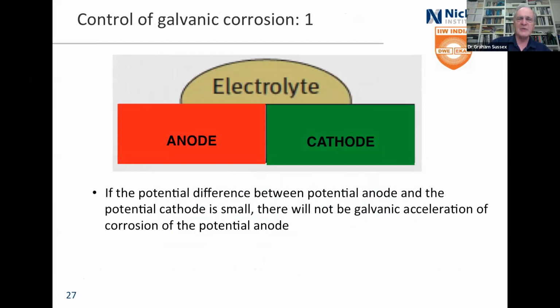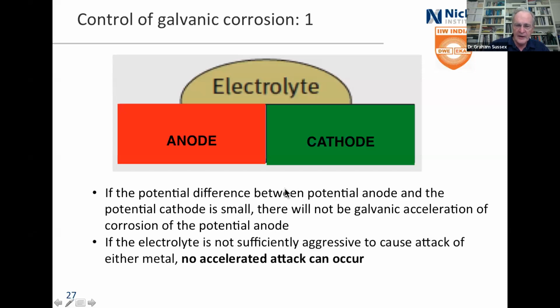So this comes out of a Euro Inox publication, and there's the reference table at the end. It's basically giving the definition of galvanic corrosion. You've got an anode, you've got a cathode, and you've got an electrolyte sitting on top. It doesn't talk about the 4 steps, but the bit down the bottom that's critical is that one of these has actually got to be able to corrode in the electrolyte that's there. Either it's got to corrode or be close to corroding. Otherwise, there won't be any galvanic acceleration. And that's what I just said there.